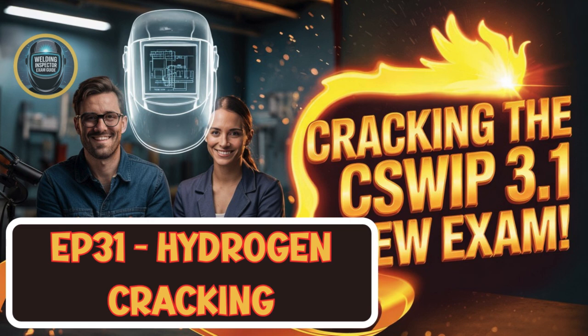The fourth is a susceptible microstructure. This means the heat-affected zone, that HAZ we talked about, has become hard and brittle. Hard and brittle. How hard are we talking? Typically, we look at hardness values. If the Vickers hardness, HV, gets above around 400, that usually signals a problem. It indicates the presence of a microstructure called martensite. Martensite. Sounds sharp. It is. It's a very hard, needle-like structure that forms in some steels if they cool down really quickly. It's strong, but it doesn't have much give.